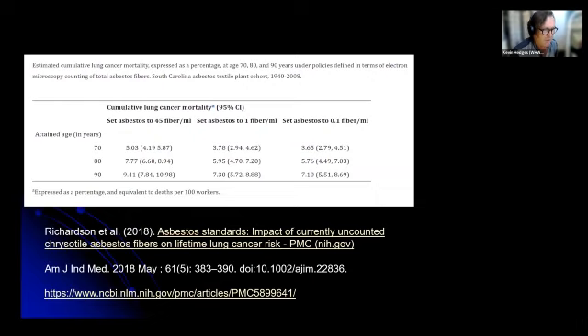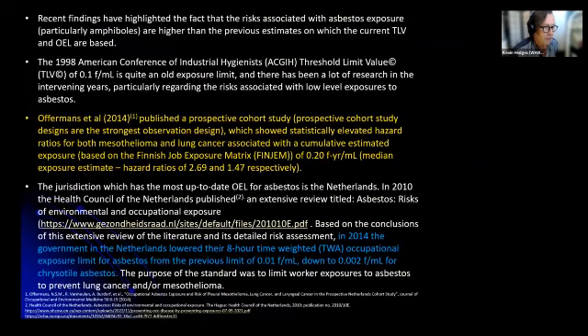What's striking when you look at these levels of risk is that we need to go well below 0.1 fiber per mil to get to a more acceptable risk. The limit of 0.1 fiber per mil is quite old; the ACGIH published it back in 1998. Offermans is a more updated risk assessment, which talks about a Finnish job exposure matrix of 0.2 fibers per year per mil exposure estimate with hazard ratios of 2.69 and 1.47 respectively, for mesothelioma and lung cancer.